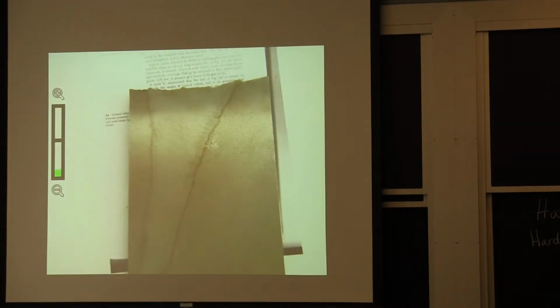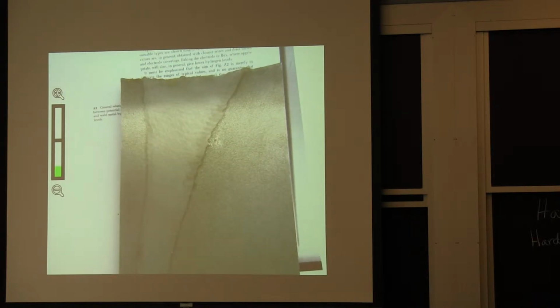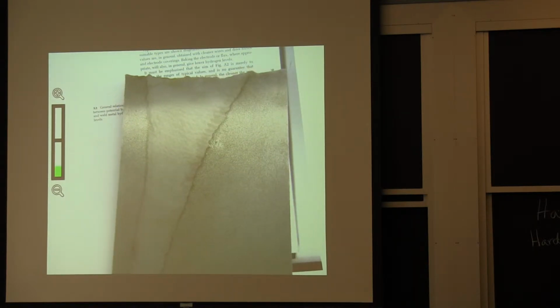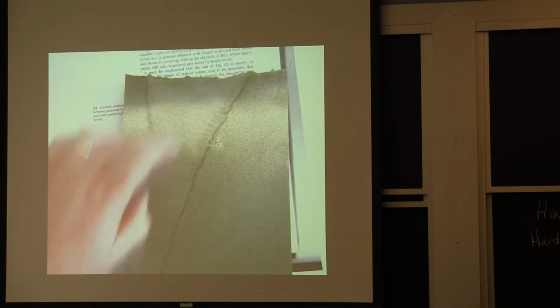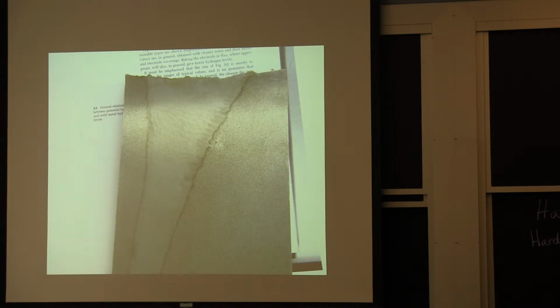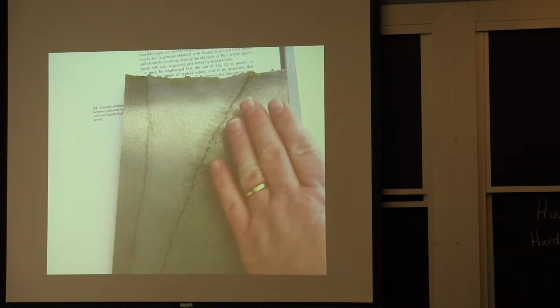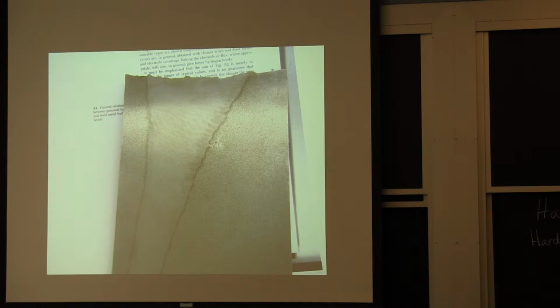This was part of a forging press. It was built originally in 1949, but it developed a crack. And it was about a 10-inch big cast steel. This is cast steel along here. This is the weld zone. They had a crack. This was a 7,500-ton forging press. They were making aluminum wheels for trucks. They were forging aluminum wheels for trucks. And you don't have a lot of spare 7,500-ton presses.